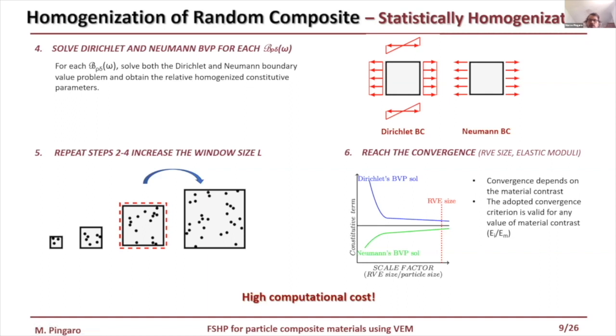Dirichlet and Neumann boundary value problems define the upper bound and the lower bound of the solution, respectively. The statistical criterion adopted to stop the procedure allows us to stop when the number of simulations necessary to obtain the average elastic coefficient does not differ by more than a given tolerance, depending on the data dispersion of the results.